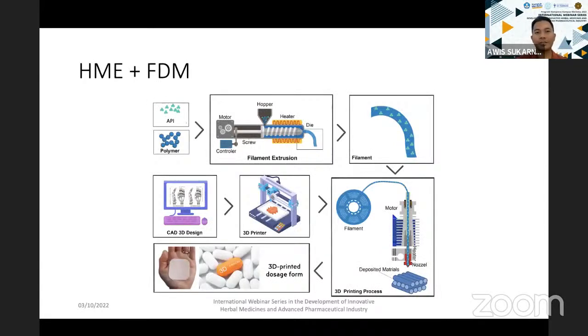Okay, so this is basically when you combine these two techniques together, the hot melt extrusion and the printer. Again, this one is the API, or in your case you can put your plant extract as well, and this one is the polymer, which is going to act as a carrier. After you put it in the hopper, you mix and melt it, and the filament that you get becomes like this. It means the active ingredient or the API is going to be suspended in the molten polymer. So the polymer is just going to act as a carrier.